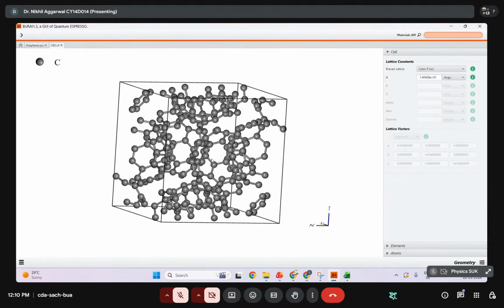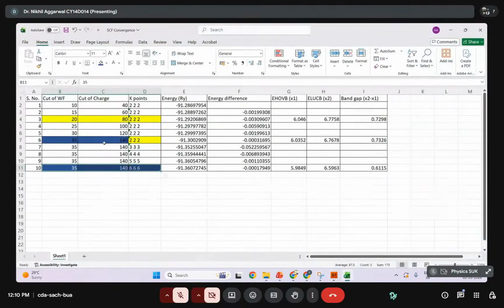Let me summarize what we have done till now. We started with the SCF convergence calculation. SCF convergence calculation brings down the energy of the system by tuning the variables: the kinetic energy cutoff for the wave function, the charge density, and the K point. We are minimizing the energy so as to maximize the stability. How? Tune the variables in a specific ratio, from 1 to 4, to 8, to 12, so that the final result remains the same. Increase the value until the energy saturates. Similarly, for the K point also, you need to increase the value constantly and watch the energy. Once you get the cutoff value, do the band gap calculation at the cutoff value and compare it with your experimental results or with the theoretical results already available in the literature.